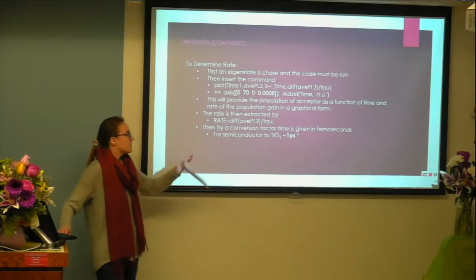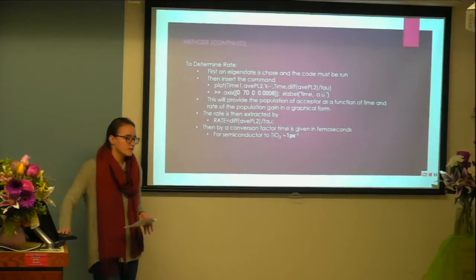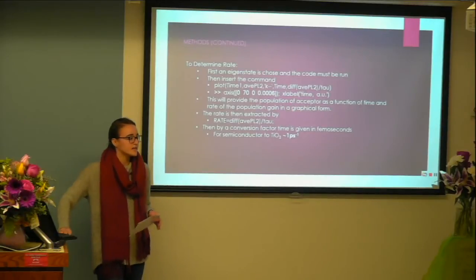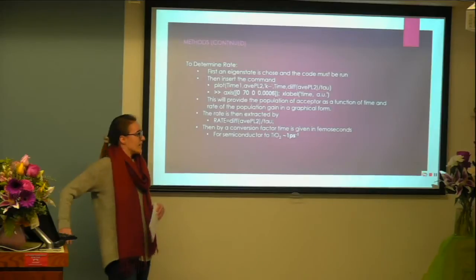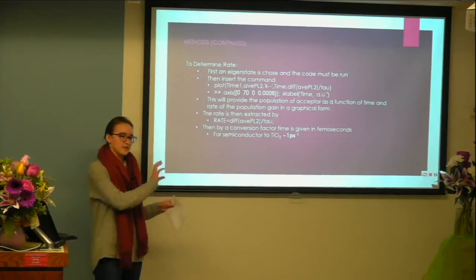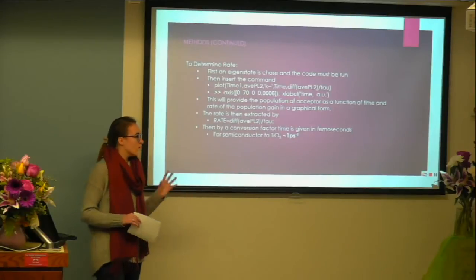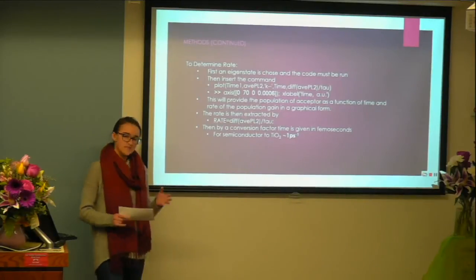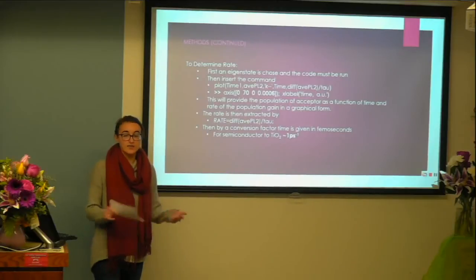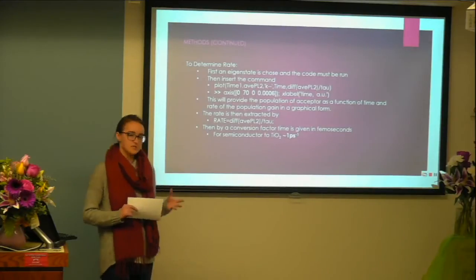Here, at about one picosecond, for an excited electron, we notice that at excitation orbitals about seven to nine, the rate of transition from the electron in the semiconductor to the TiO2 agent was about one inverse picosecond. It's predicted that without excitation of the electron, that rate will be close to zero.